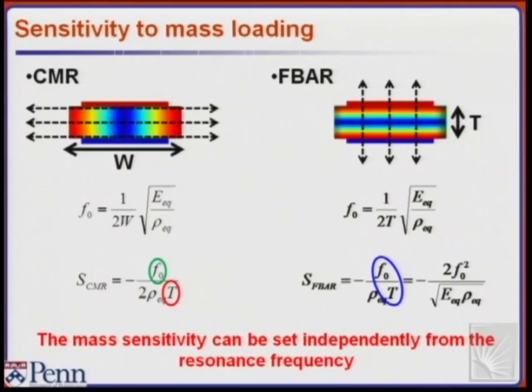Once you set your frequency, you can adjust the thickness to adjust your sensitivity level. And that's unique because there are applications in which, for example, you want to design a sensor at 433 megahertz, which is one of the standards, or 920 for the ISM bands. At that point, you really need a certain sensitivity level and a fixed frequency. With an F-bar, you'll be stuck. With a quartz crystal, you will be stuck at that frequency and with that sensitivity. Here, once you have the frequency, you can still set the thickness independently.